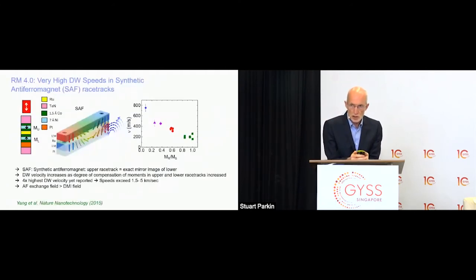And I mentioned earlier this concept of a synthetic antiferromagnet, where an upper and lower racetrack, otherwise identical, one is a mirror image of the other through, in this case, I hope you can see, this ultra-thin ruthenium spacer layer that will give rise to a very strong antiferromagnetic coupling, where it turns out the chirality of these Néel domain walls is preserved from one racetrack to the other.